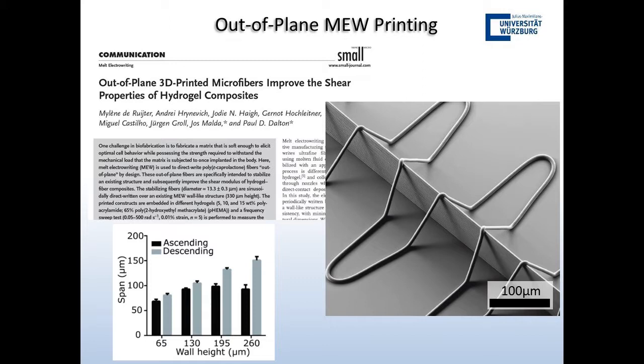another reason. We were finding that we could, this is work in Würzburg, we actually printed a wall of PCL, and then on top of the wall we threw a fibre back and forth, oscillating, to kind of hold this down like a tent string so that it doesn't bend and buckle. But I want to highlight here that the ascending fibre and the descending fibre are positioned at a defined point away from the wall. And we found that this is very, very reproducible across multiple samples.